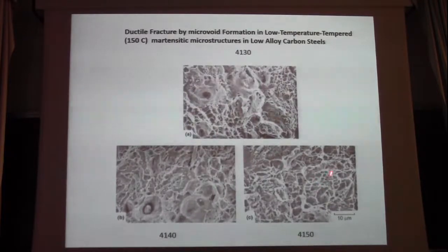Each one of these little voids has a hard particle. I found out over the years, and it took a long time to find this, with hardworking graduate students, which is really important, that during austenitizing of these medium carbon steels, there's a lot of hard carbide particles left over, and these microvoids form around those particles with continued deformation. If you have big inclusion particles, you get big voids in the structure. But these were fairly clean structures. So this is ductile fracture.